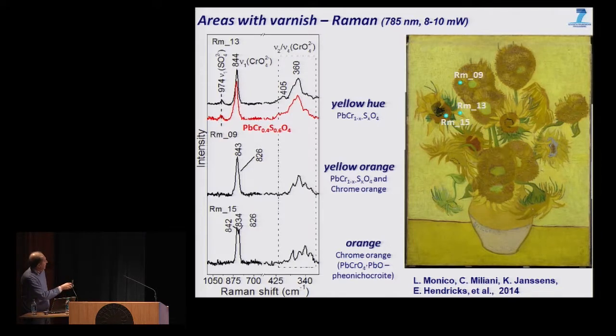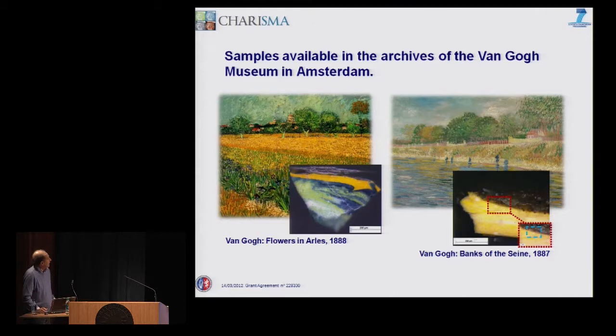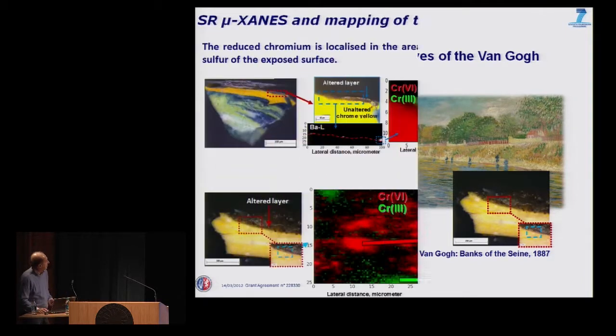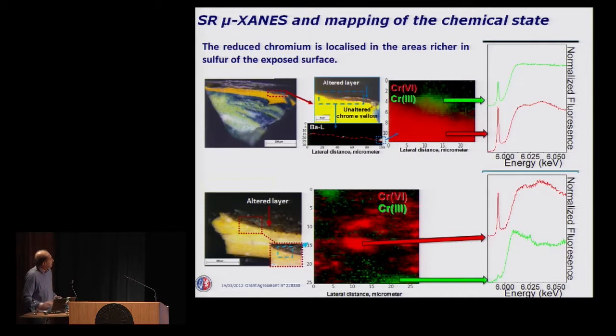While in other regions, the yellow-orange was characterized, in mixture with some co-precipitated chromate and sulfate. And also in other parts, the orange pigment was found, the phoenicochroite, the co-precipitate of chromate and lead oxide. No possibility to sample to verify if there was some alteration present there, but samples were available on other paintings in the archives of the Van Gogh Museum, and measurements at the synchrotron permitted to identify the presence of chromium-3 at the surface of this sample, for example, that showed to be particularly rich in sulfur.